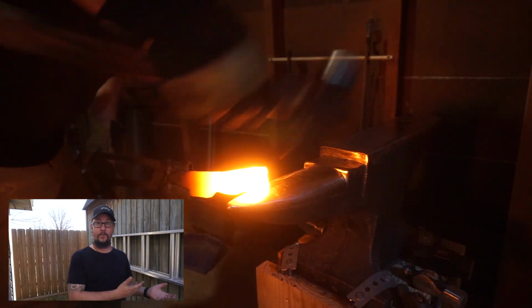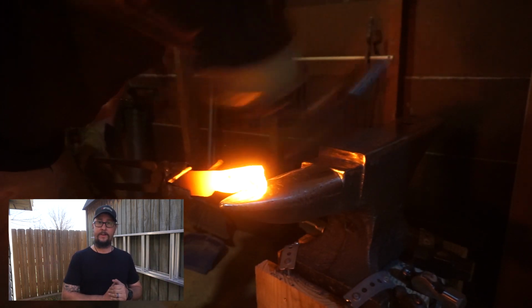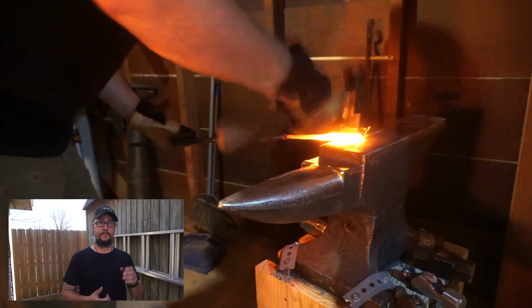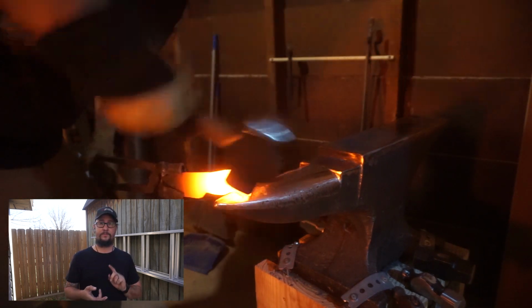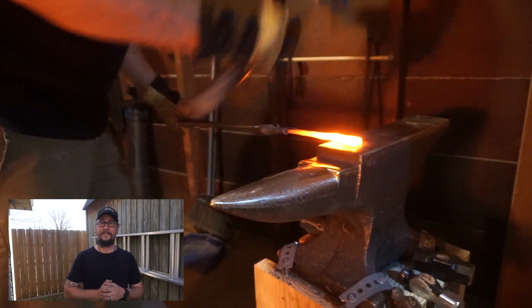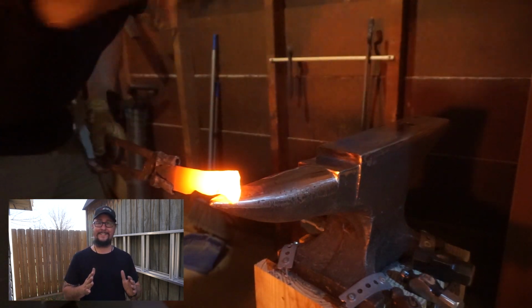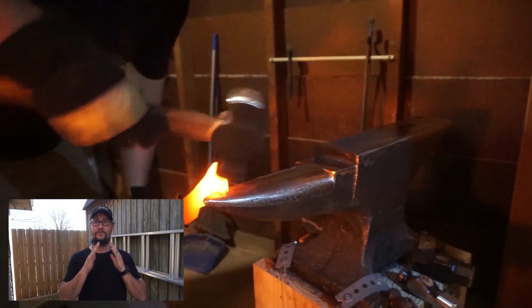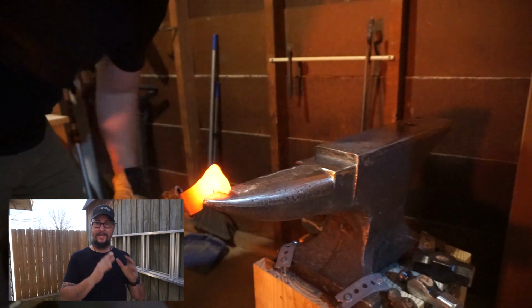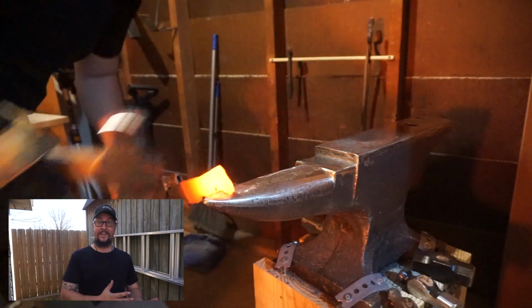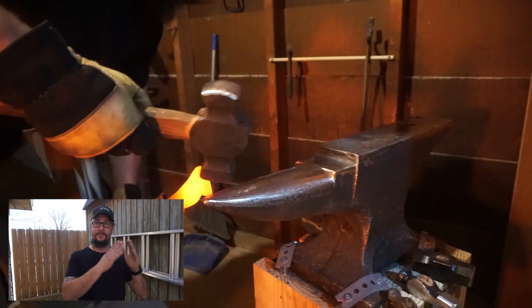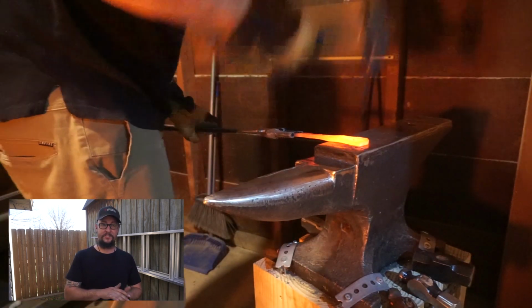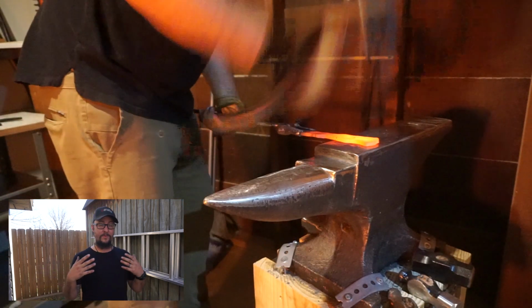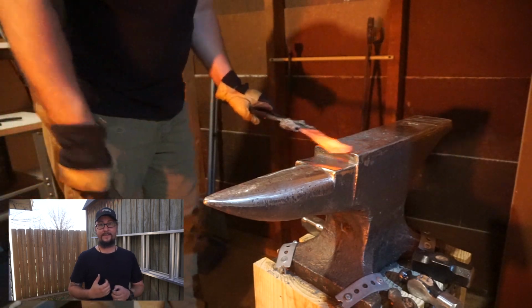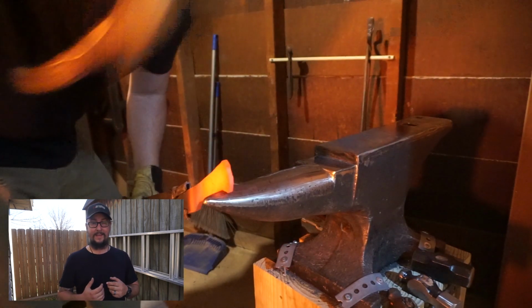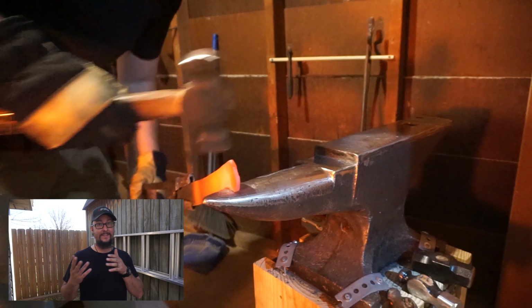You can use a regular home oven, or if you're brave enough, you can temper it with a torch. You can temper it with your forge. You can do pretty much anything that you need to. The goal is to get a straw-colored finish on the blade when you're done. That is the temper that a lot of people are looking for. If you get to a blue finish, you've most likely tempered the hardness too far back. But you can be tricked into thinking that